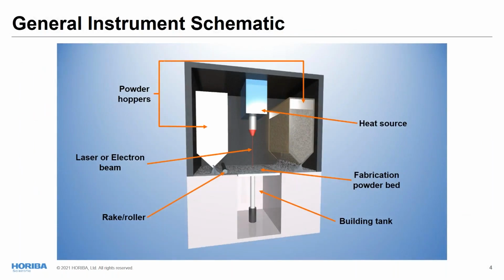But today we're going to talk more specifically about laser printing. I'm sorry, not laser printing, but metal printing. And there are two main systems for printing using metal. You can either use a laser or electron beam. You have a chamber, and if you use the laser system, you're going to be using nitrogen or argon in the printing chamber.